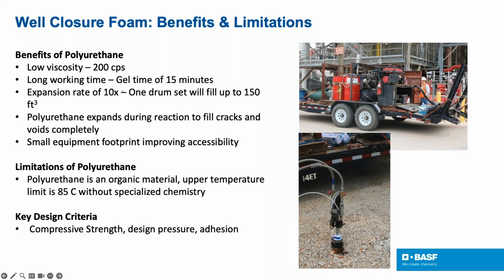Limitations of polyurethane, because it's an organic material, the temperature limit is about 85 degrees Celsius without any specialized modifications to the basic chemistry. And then some of the key design criteria would be compressive strength, design pressure, and adhesion to the pipe.